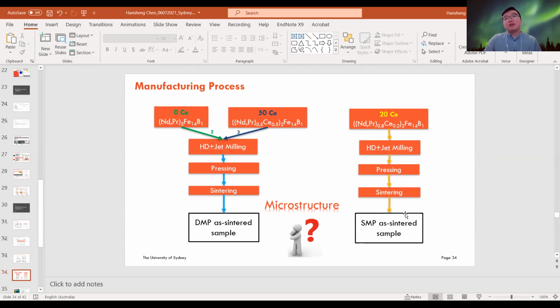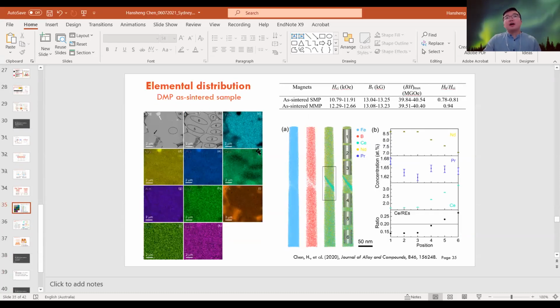And then we can see the manufacturing. We prepare some 0 cerium and some 30 cerium here, with a mixing ratio between 2 to 3, adding them together. After the typical HD hydrogen decrepitation and jet milling, and after pressing these magnetic powders together and then sintering, we got the so-called dual main phase sintered sample. And then we can know that the average cerium concentration here is 20%. 20 here means cerium takes up 20% of the total rare earth elements. As a comparison, we fabricated the single main phase sample. And then we can see at the micro scale the cerium here.